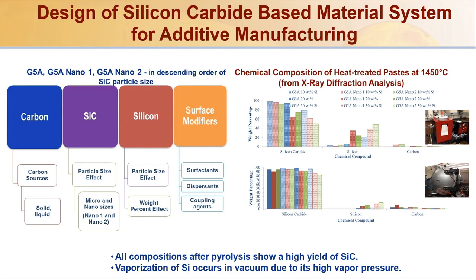If you look on the left side, we used different types of carbon sources, solid, liquid, and silicon carbide. We also studied the effect of particle size, micro and nano sizes. Then for silicon, which was also filled in that paste or starting material, we studied the particle size effect and weight percent effect. And then there were a number of surface modifiers, in terms of surfactants, dispersants, and coupling agents.